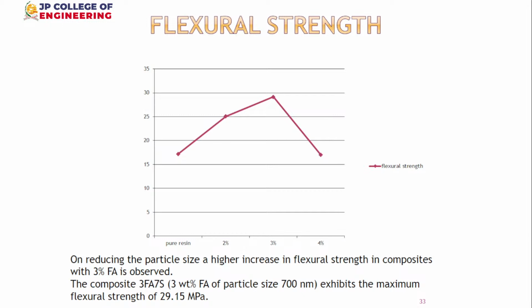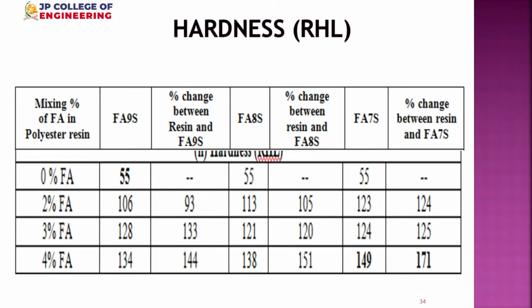Next slide, please. On checking the hardness, hardness goes almost uniformly, whereas in flexural we can see there is an inversion. 2% low, 3% high, again 4% is low. So one can say, yes, 3% is my optimal value. But for hardness, as you increase the percentage of fly ash, hardness continues to increase. Therefore, from the hardness point of view, you can see the last column, the 4% added, even at 700 nanometer. Particle fineness means hardness is more. That is again a good observation.